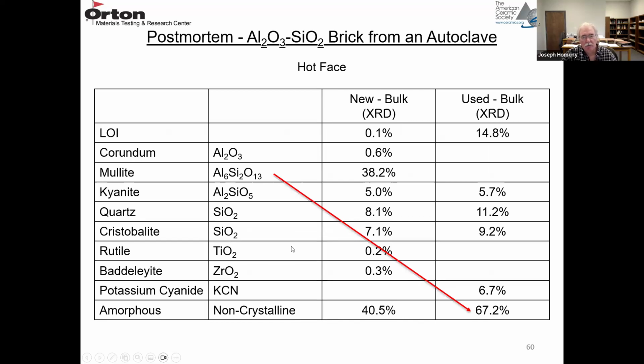So we also did X-ray diffraction, XRD, on the new refractory and then the used refractory at the hot face. Prior to running X-ray diffraction, you usually run a loss on ignition. So this is probably run around 800 or 900 degrees C. You remove the volatiles. So the new material had maybe some water picked up, only 0.1% loss on ignition, but the used material had a high loss on ignition, almost 15%. So here is the corundum content, Al2O3, 0.6 in the new material. It's no longer present in the used material.